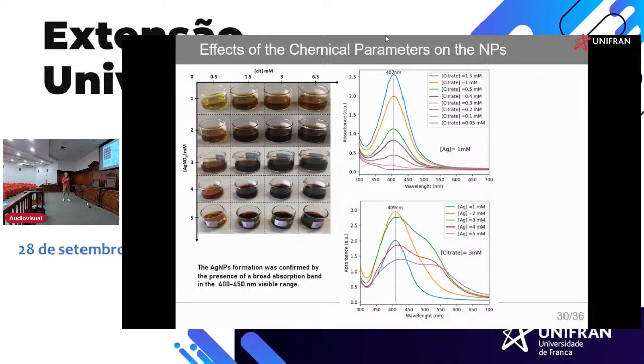The peak is quite symmetric and very narrow, which is very good. But at high concentration of citrate, for example 3 millimole, when we increase the concentration of silver, a shoulder appears, leading us to think that there are two particle sizes inside, one bigger than the other. So if we want just one size, it's not a good solution.